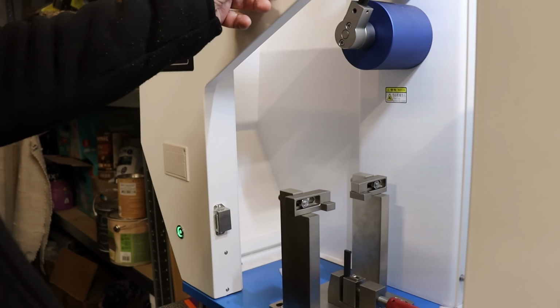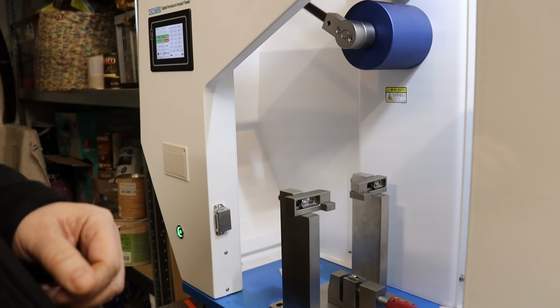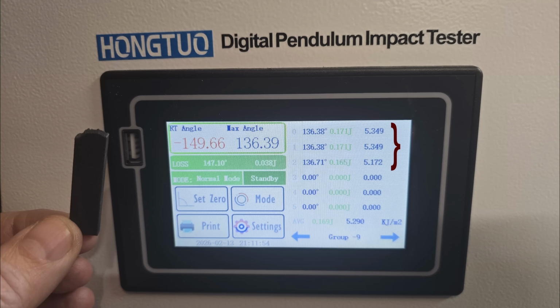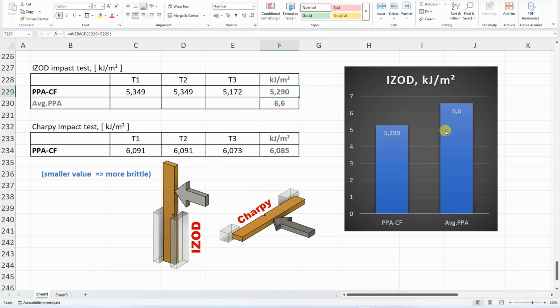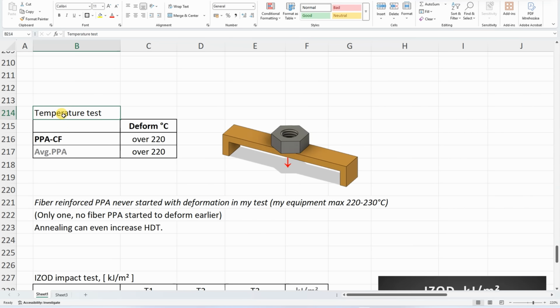IZOD is the first test, and measured numbers again in the right upper corner. Overall, PPA-CF is quite a brittle material, and this filament is a little bit weaker compared to the average PPA. But still, this is, let's say, 2 times tougher compared to the average PETG. Just a few words about my temperature test.